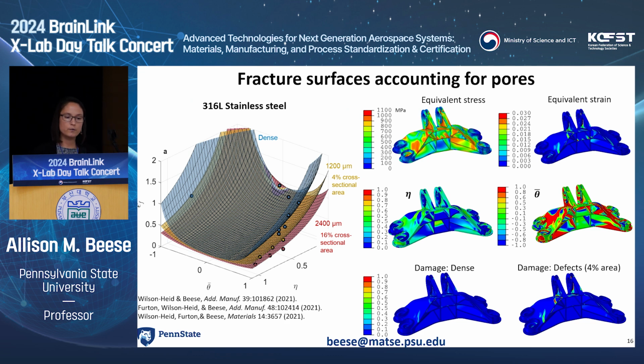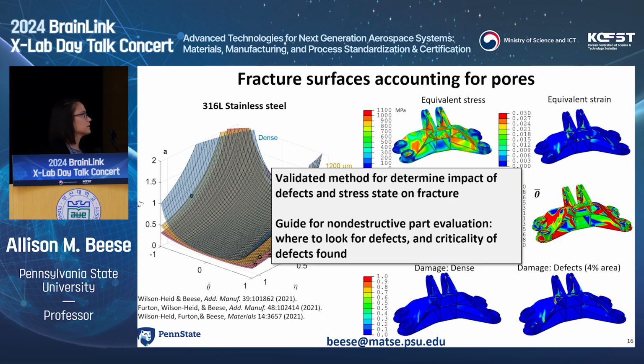So this tells us that we can take a look at a material and a design, and we could adjust and say, what are the areas that I really need to inspect for pores and of what size? And then do I need to redesign this material at all to actually use it? So the thing about this is now we have this method that allows us to determine the impact of defects and stress state on fracture. So we know the ductility based on these things. And it also gives us a guide for non-destructive part evaluation. So it tells us where we need to look for defects, and it also tells us the criticality of the defects found. And we can flip it to say, what is the critical size of defect I have at every point in my material, and look for that as well.